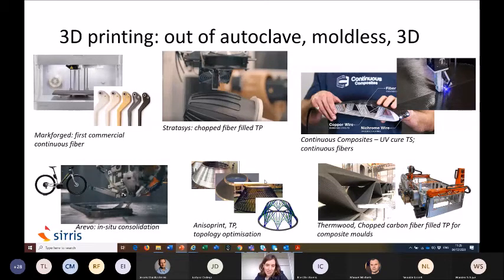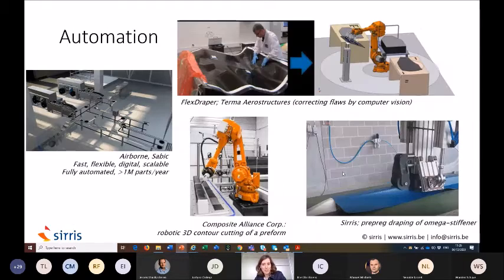Example from Anisoprint. This is a part that was traditionally made in aluminum. They changed to a composite-centric structure, and now they are redesigning that with topology optimization. So you only use your material where you actually need it in your parts. So this is very interesting technology. This is Thermwood. This is at larger scale, I would say. So this is for making molds. This is the mold for a helicopter blade. Very interesting technology. I see that my time is almost over, so I will speed up a bit.